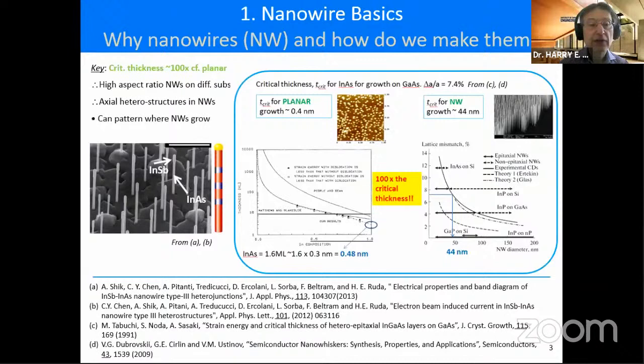So what's going on, if you're looking on the left, for example, is the case of indium arsenide as the initial nanowire, and then we change the growth longitudinally to indium antimonide. What you can see is that those wires are growing without constraint of material around them. So when there's strain, they can change their dimensions to reflect that additional strain energy. And indeed, if you look at the indium antimonide on top of the indium arsenide, you'll see that it's actually sort of blown up a little bit, like a match head on top of a matchstick. And so that's the point, is that you have this ability to accommodate that strain by changing dimensions, which you don't have if you're trying to register a plane of atoms with every atom in configuration with its neighbor above its head in planar growth.